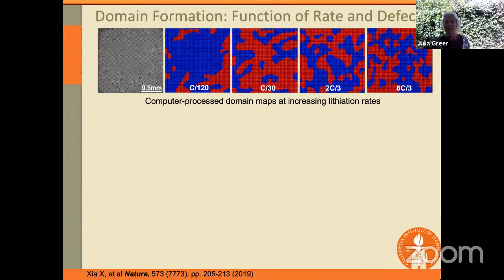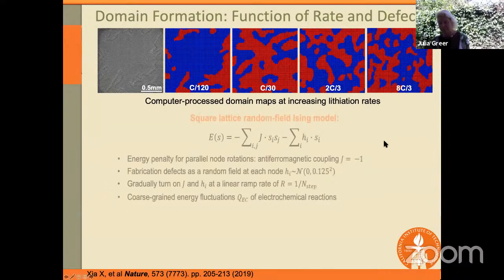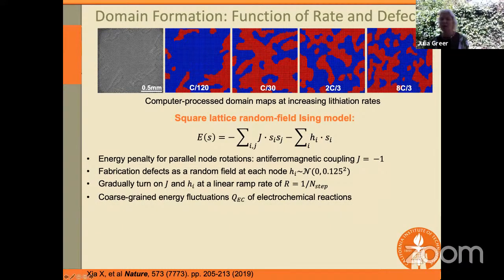And so what we uncovered is that these domain boundaries of the frustrated buckling patterns seem to correlate with the lithiation rate. So when you lithiate very slowly, so here's your C/120 lithiation, it's very slow, it forms one large domain. And when you lithiate very fast, you can see that it's forming much smaller domains and more of them. So effectively, to us, it looks like a model treatment for the so-called Ising model, where you have these ferromagnetic and anti-ferromagnetic switching behaviors.